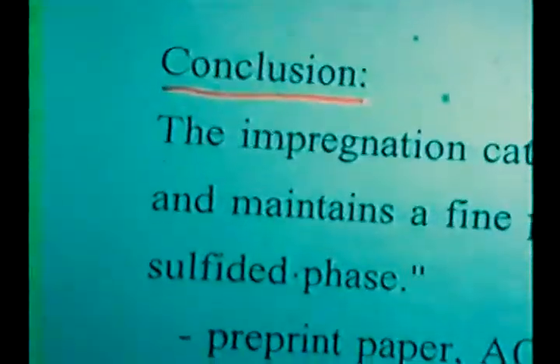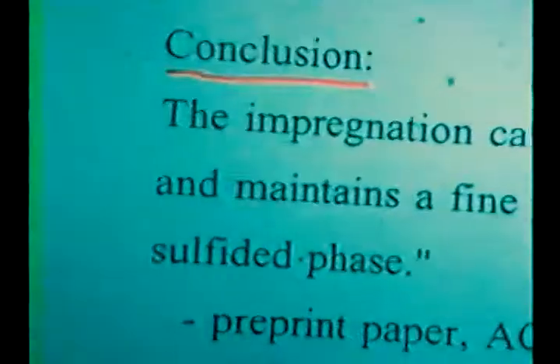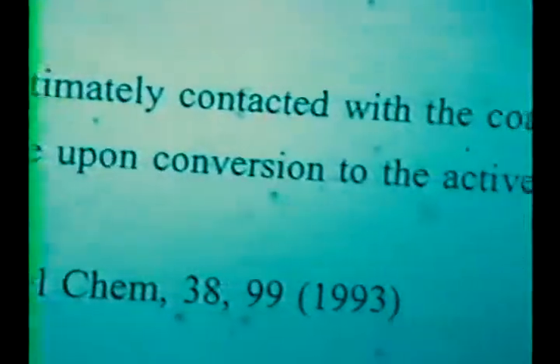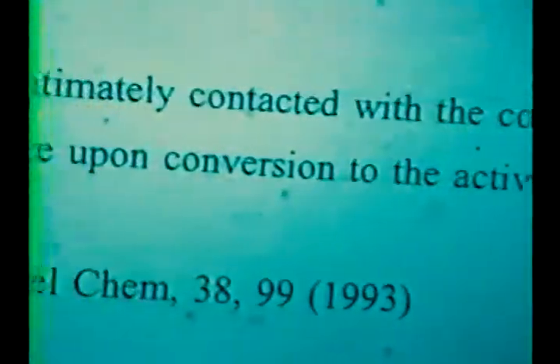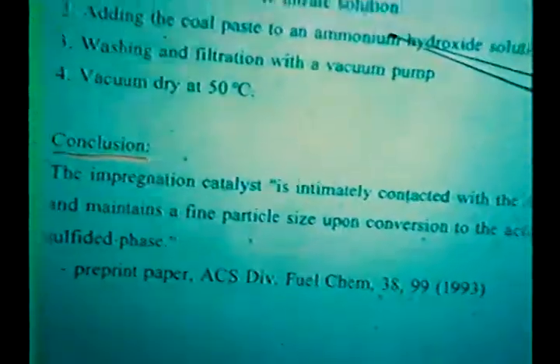And they found this method is much better compared to another method they call the physically mixed catalyst, which means, just as I mentioned, first you prepare the ferric nitrate solution and then add ammonium hydroxide to the solution to get the precipitate, and then get the ferrihydrite catalyst, and then mix it with coal and react it in a reactor.